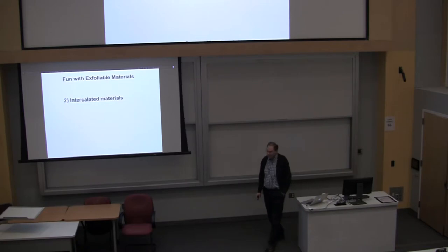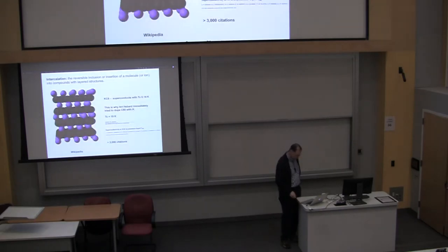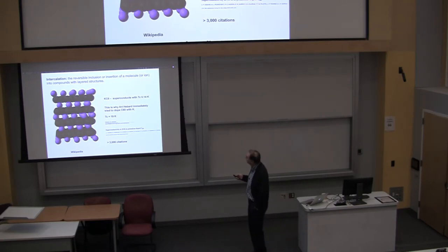Okay. So you can do all kinds of stuff on the single layers. You can also start intercalating these exfoliable materials. So here's an example. Intercalation is the reversible inclusion or insertion of a molecule or ion into compounds with layered structures. And so here's an example, potassium-doped C60. It superconducts with a very low Tc. So years ago, when C60 was discovered, one of the first things Art Hebard did was to put potassium in it, because he knew that when you do it with graphite, you get a superconductor. So he said, well, we'll try it with carbon-60. And he got a superconductor with a 19 K Tc. And so that was a huge result and drove a lot of interest in it. But that's why he did it right away. He knew to do that.